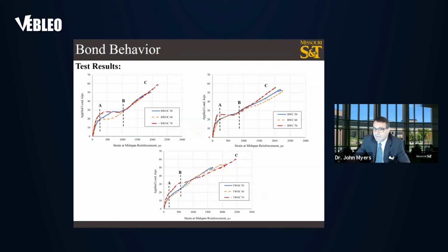In order to investigate the effect of cement replacement on strain behavior, the recorded data for each group, BWOC, BWC, and TWOC, were plotted in load versus strain format as shown in the figures. According to the plots, each group of specimens displayed almost similar behavior during testing except for the preflexural cracking stages of 70% cement replacement. The 70% specimens had much greater crack load than the others did. The results of the measured strains indicated that each specimen ultimately failed due to the bond around the splice rebar.